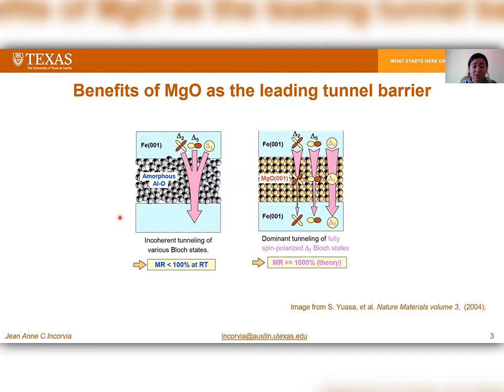Amorphous aluminum oxide was the barrier material first explored, and it resulted in incoherent tunneling of the various Bloch states, which therefore resulted in an MR ratio of less than 100% at room temperature. Further moving on from aluminum oxide was magnesium oxide, which was crystalline in nature and resulted in a dominant tunneling of fully spin polarized delta-1 Bloch states. In theory, this predicted an MR ratio of way higher than 1000%.